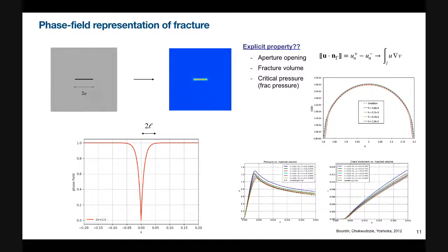And in these two figures on the bottom, we compared pressure response. So this is pressure versus injected volume, and this is crack length versus injected volume, with different mesh sizes. And so we are able to verify that the model can calculate fracture length and also the critical fracture propagation pressure.